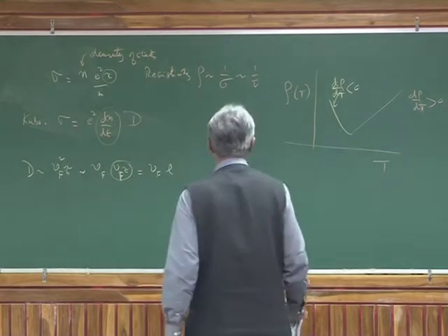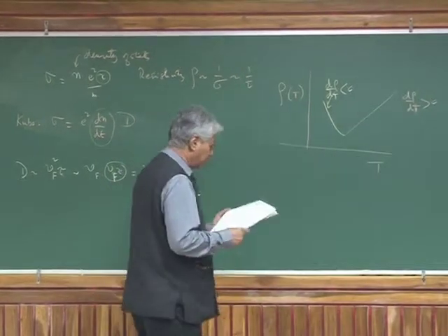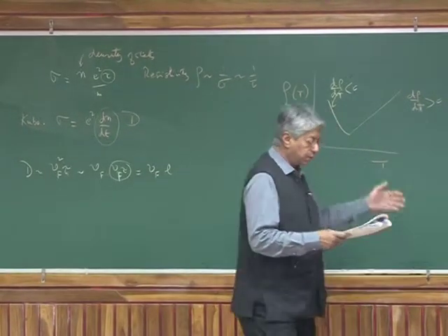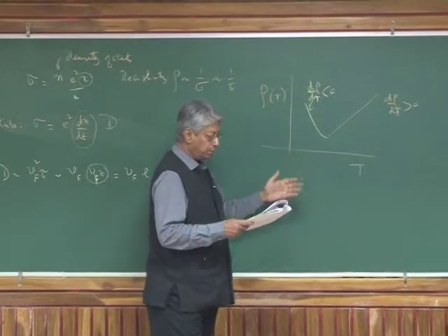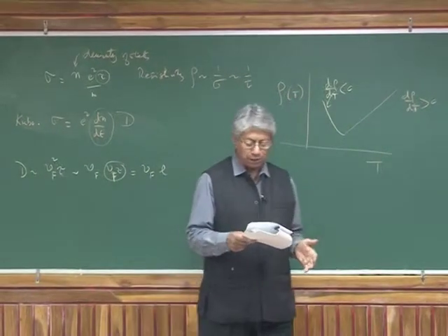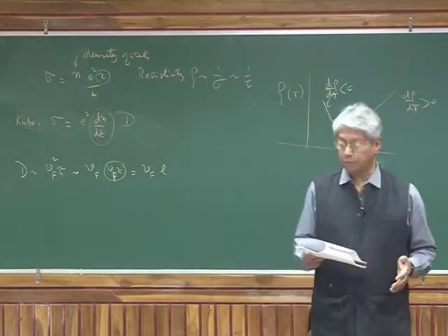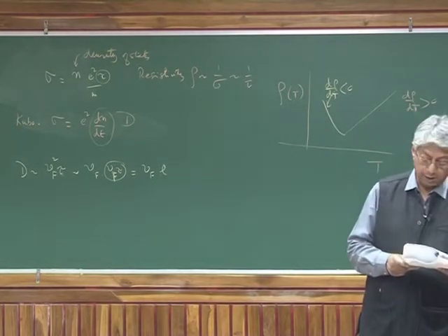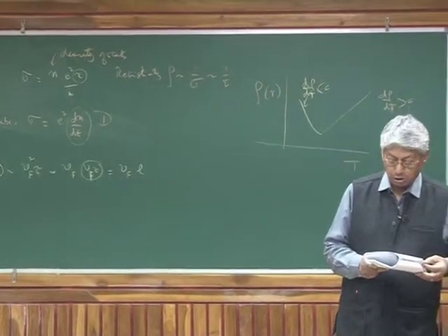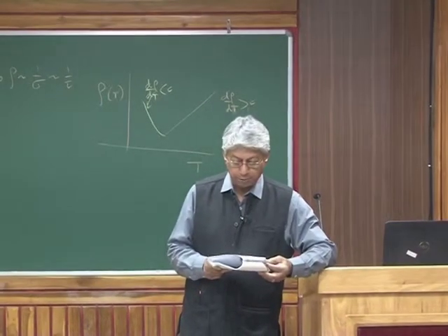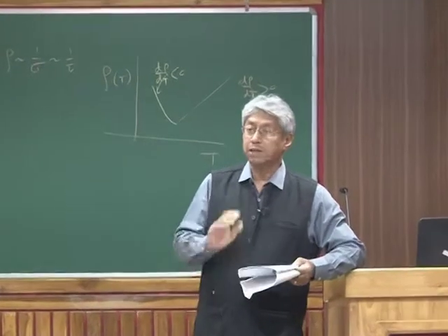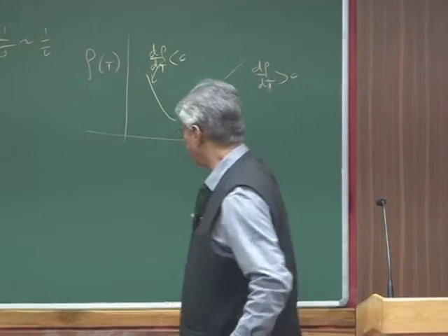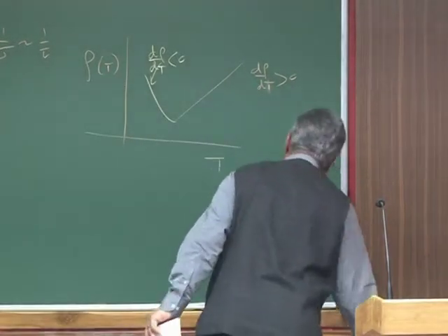All right. So let me just read out again. In particular, the temperature dependence of the resistivity becomes much weaker and eventually changes direction for high enough disorder. There's some empirical rule called the Matthiessen rule, according to which the contributions to rho due to disorder and temperature are additive, and this breaks down. All those rules break down. So Mooij, spelled M-O-O-I-J,